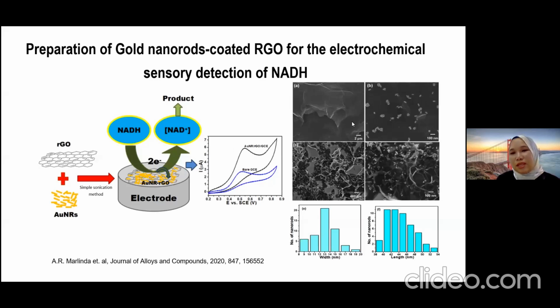So the FESEM image here shows, in figure A, only the reduced graphene oxide, and this is for the gold nanorod. After fabrication, we can see that there is a lot of gold nanorod coated on the reduced graphene oxide sheet. Okay, with the width of the gold nanorod of 13 nanometer, and also the length up to 44 nanometer.